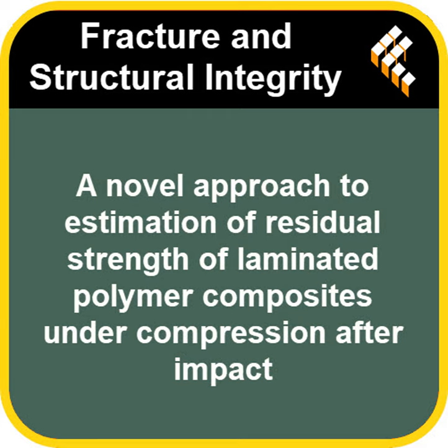At the low energy levels, say around 10 to 20 joules, they saw the material deform under load, reach a peak, and then smoothly unload, kind of springing back. Internally, this matched up with the very first signs of damage, often invisible matrix cracks starting, and the beginning of delamination between layers. Then you move up to medium energy, maybe 30 to 50 joules, and things get more dramatic. You see a sharp drop in the load right after it hits its peak. That tells you the material is rapidly absorbing a lot of energy.